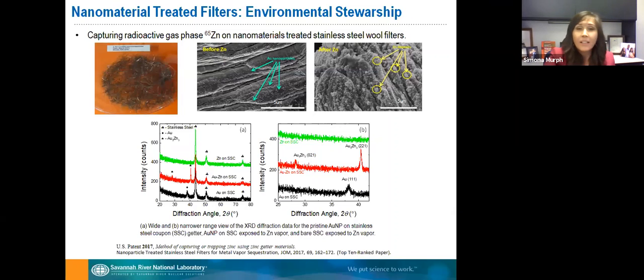And another way of implementing these nanoparticles is we use them as a filter to capture some gas phase zinc vapors. And zinc 65 is also a radionuclide that is a byproduct in the tritium facility. I'm not going to go into a lot of details about this, because some of it is more critical to the business. However, it was found that some of the radioactive material came through the pipe and got to the glove box of the worker. So of course, our main priority is not to expose people to radioactive materials. So the goal was to create a filter that can capture the radioactive materials.